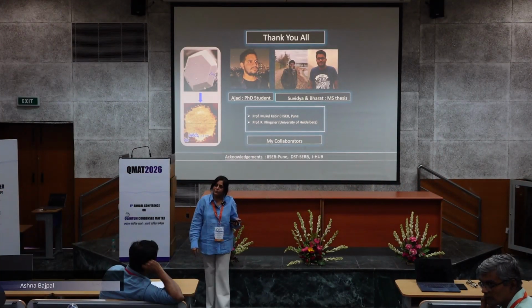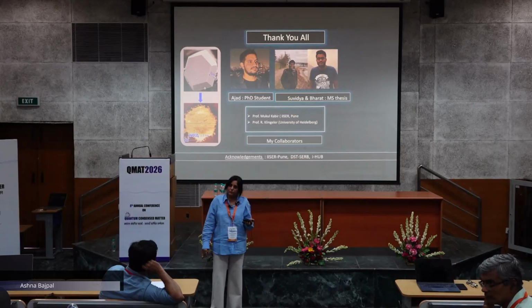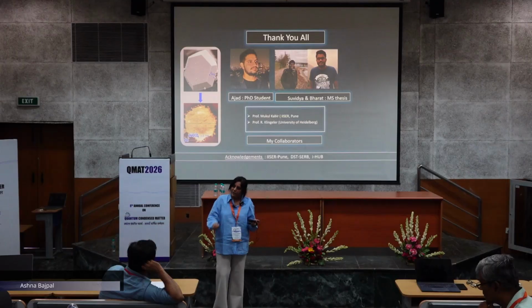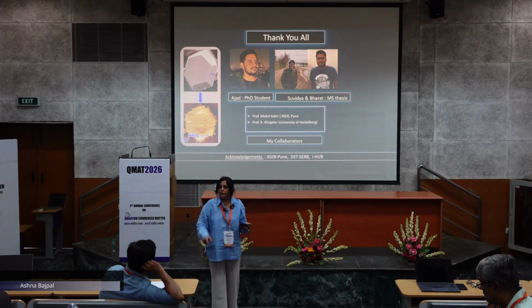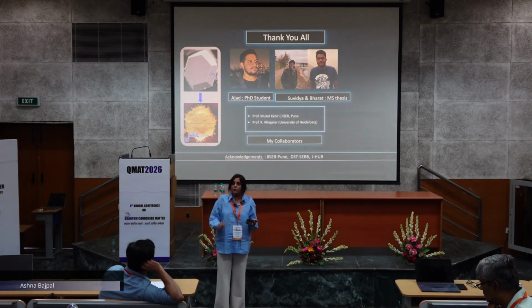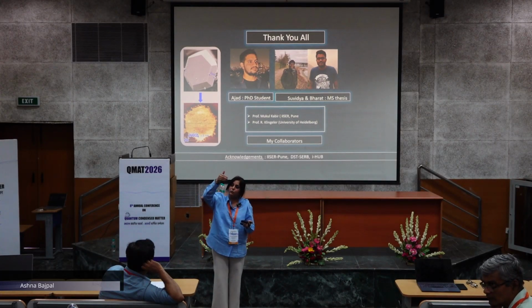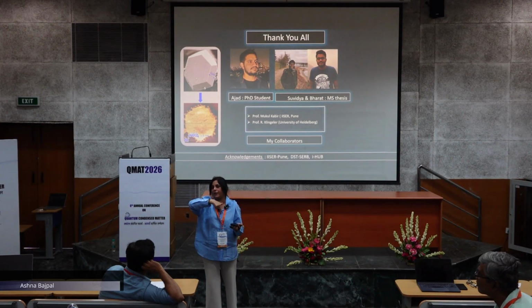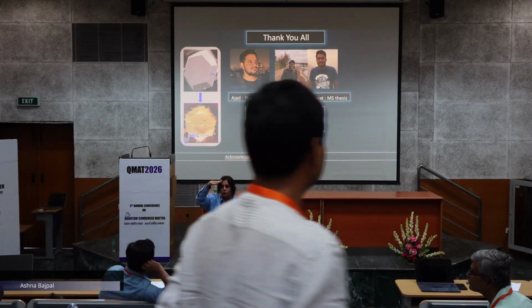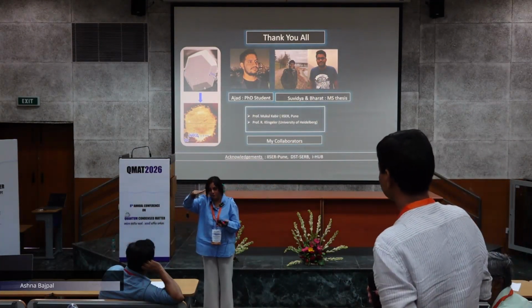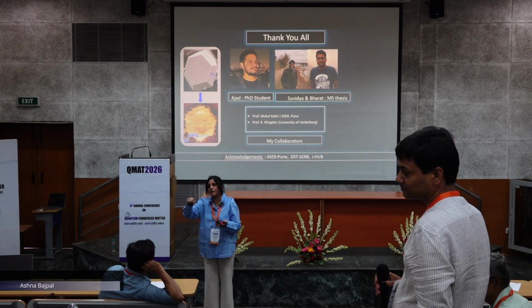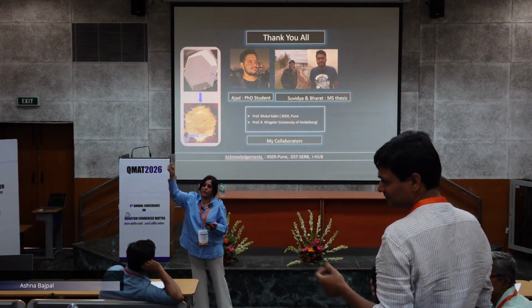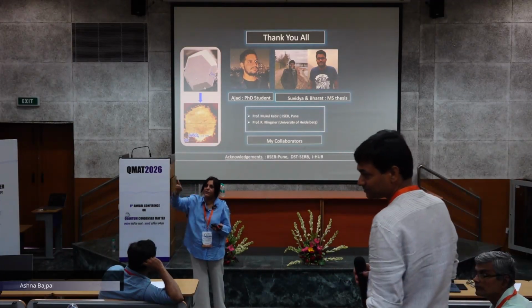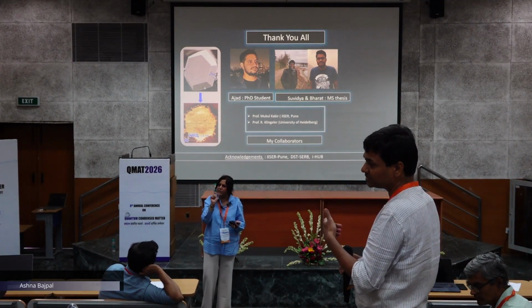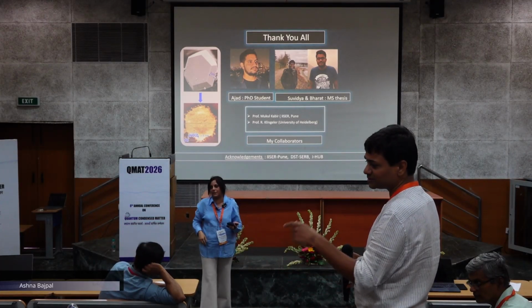If you were to take the proposal of screening them seriously, then because these are thermally excited, there would be a temperature dependence in the reduction of the Curie-Weiss moment. Do you see this reduction as a function of temperature? So not reduction, because it is not fitting to the Curie-Weiss law, we couldn't get the effective moment. But for all other systems, I could see linearly increasing magnetization as a function of temperature at a given magnetic field. In this case, it is increasing actually. That's what I am trying to tell. It is increasing as a function of temperature in the paramagnetic region. It's a very strange system. So we could discuss later, yeah.